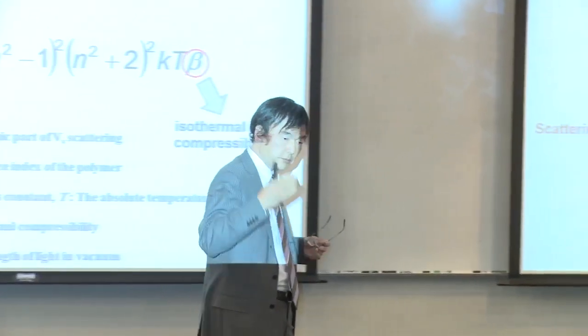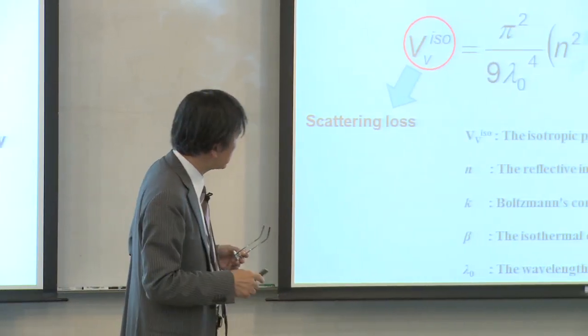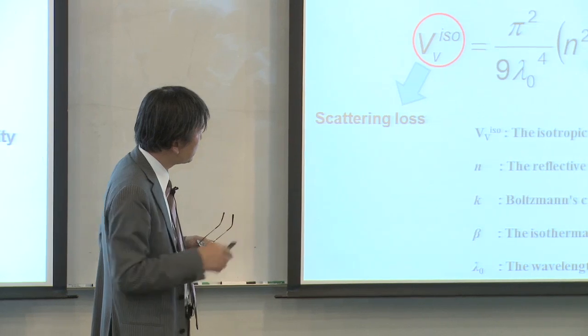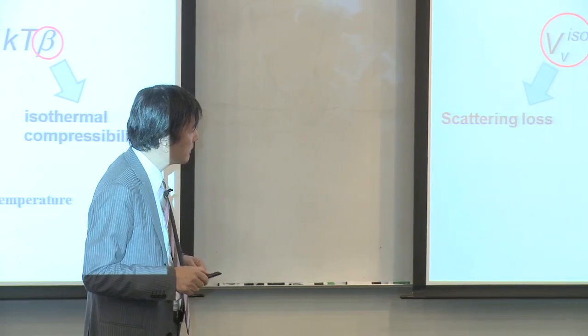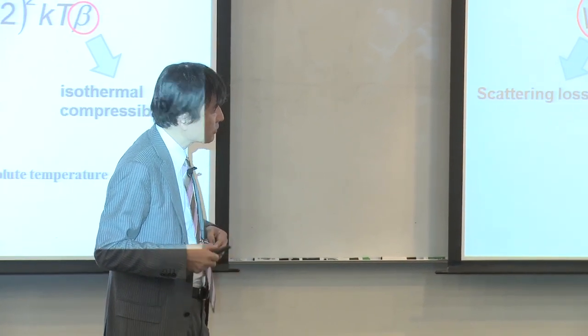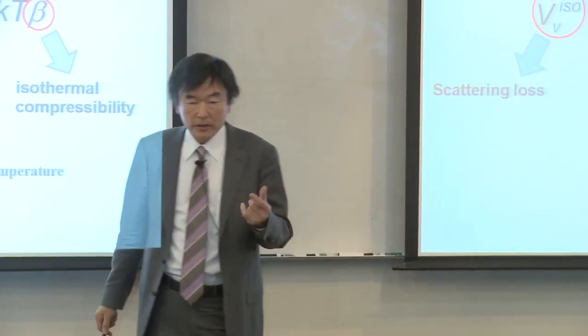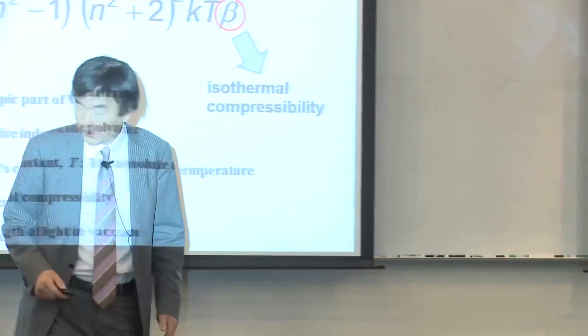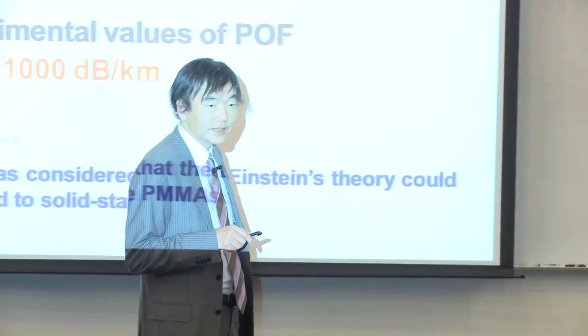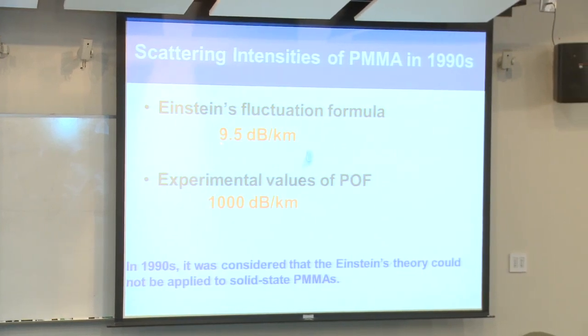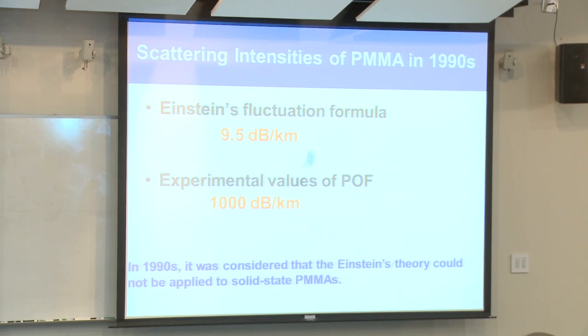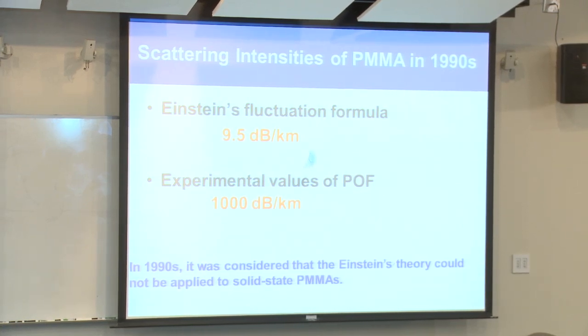will be isotropic. This is vertically polarized light path, and the vertically scattered. Then this is the definition of the VV scattering. This is isotropic VV scattering. It's proportional to beta, that is the isothermal compressibility. So I measured the isothermal compressibility of the polymer materials used for POF, then estimated the VV scattering loss. Wow, it's less than 10 dB per kilometer. Although the experimental result is 1,000 dB per kilometer, this is really, for me, the light for the future in the research. But the question again, what is the difference between theory and the experiment